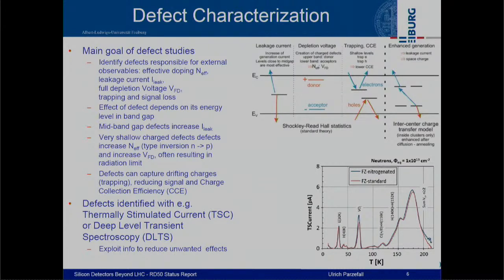One tool we use for this is thermally stimulated current, or TSC, measurements, where you can identify individual defects, like here a vacancy oxygen cluster, with the aim of exploiting that information to reduce unwanted defects.